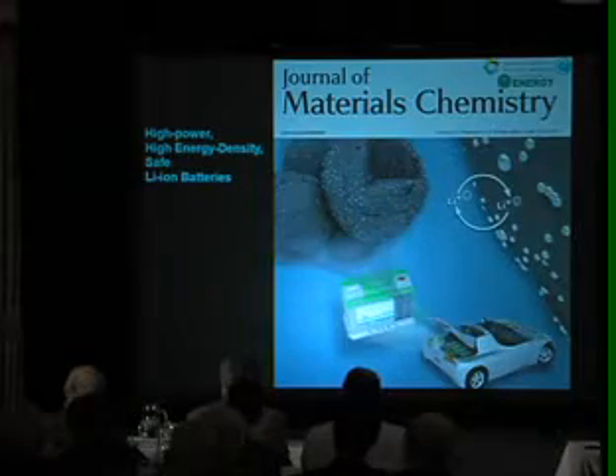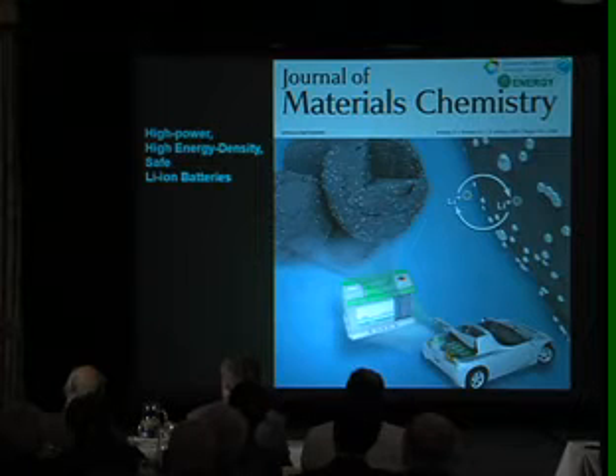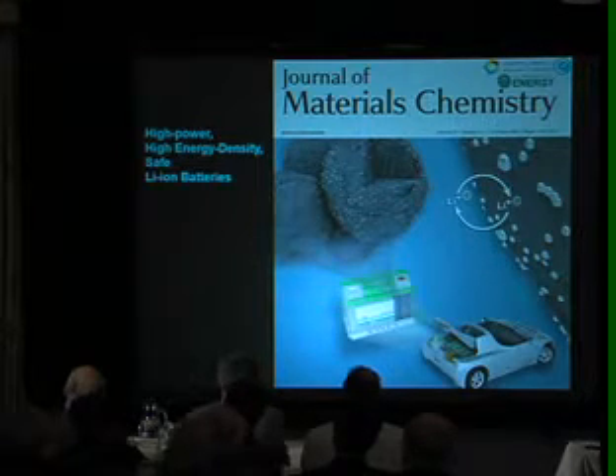So smaller nanoparticles of metal, perhaps mixed with the graphite, Sony realized, might be advantageous. But the problem that they encountered was that they tried to force that marriage by grinding the two materials together. If you look by eye, it looks as if you've made a mixture, but in fact no intimate contact is actually achieved, and the performance is only marginally better.